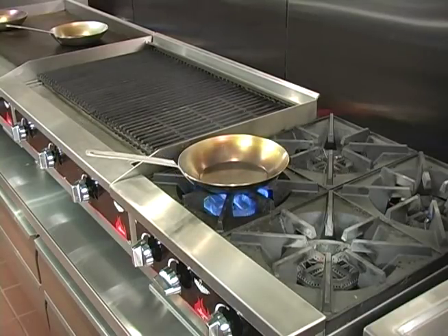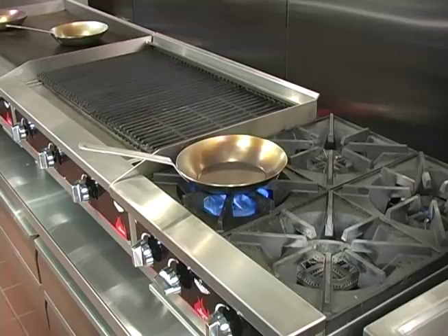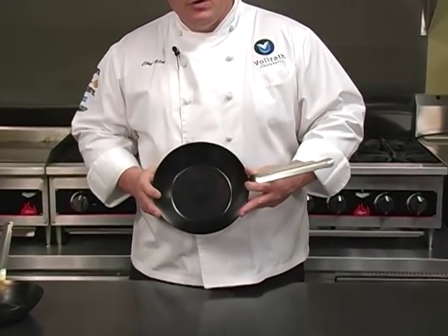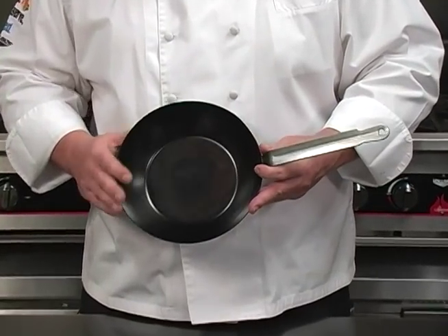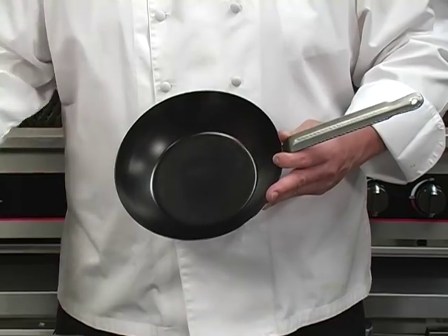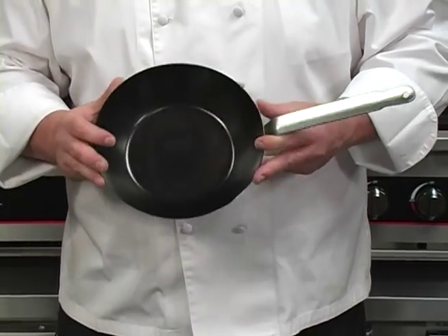You can see now that the oil has reached its smoke point — it's beginning to evaporate and form that cross-link to the previous layer. You want to repeat that process of these thin layers back to the heat and so forth. This pan we've done 11 times, and you can see our surface is now a very hard, smooth, very durable surface. I can't emphasize enough to use very thin coats of the oil, back and forth through the heat.